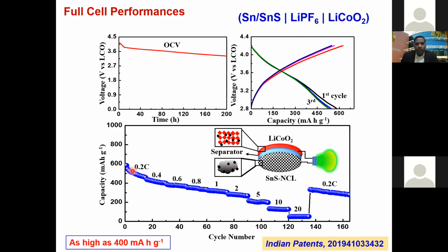And the capacity has been obtained at a different C rate. And you can see that you get a full cell capacity at the 0.2 C rate as high as 400 mAh or 500 mAh, which is at least double compared to the capacity of the conventional lithium-ion battery. And you can see that even at a very high C rate of about 10 or 20 C, the capacity is still higher than 100 mAh, which is very important for practical applications.